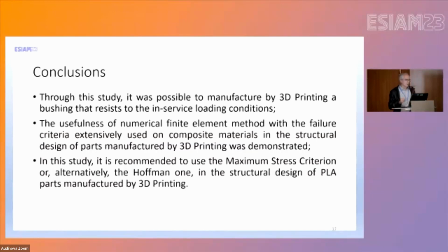As conclusion, through the study it was possible to manufacture by 3D printing a bushing that resists the in-service load conditions. The usefulness of the numerical finite element method with the failure criteria extensively used in composite materials in the structural design of parts manufactured by 3D printing was demonstrated. In the study, it is recommended to use the maximum stress criterion or alternatively the Hoffman one in the structural design of PLA parts manufactured by 3D printing.